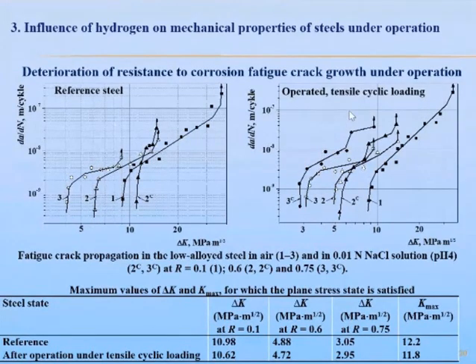And so hydrogen-assisted degradation of the carbon steel operated under tensile and compressive cyclic loading was manifested in degradation of plasticity and impact toughness, and also the fatigue growth rate in the post-operated steel was accelerated in a corrosive environment, especially at the higher stress ratio, and the kinetic diagram indicated its susceptibility to stress corrosion fatigue.